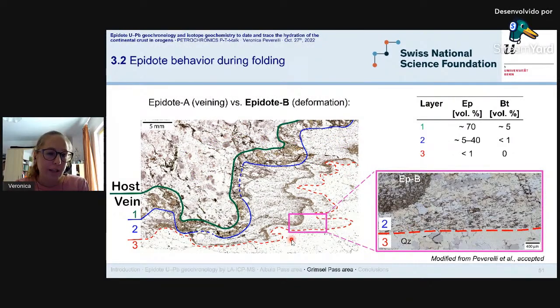And quartz in layers 2 and 3 is almost entirely dynamically recrystallized by subgrain rotation recrystallization, as you can see from the shapes of epidote grains in this figure. What we are particularly interested in is how the microstructure in layers 2 and 3 formed. From now on, we will call epidote that precipitated directly from a fluid, so epidote in layer 1, epidote A. And epidote in layers 2 and 3, which has something to do with deformation, and we will see what, we will call epidote B.